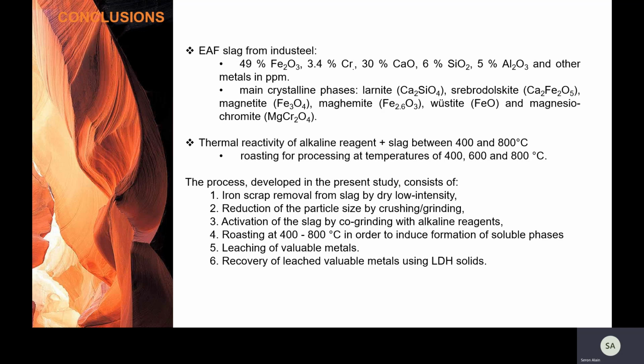TGA results clearly demonstrate the reactivity of the alkaline reagents mixed with slag when treated above 400 degrees C. Consequently, the roasting temperatures chosen in this study are 400, 600, and 800 degrees C. The process developed in the present study consists of iron scrap removal from slag by dry low-intensity magnetic separation, reduction of the particle size by crushing and grinding, activation of the slag by co-grinding with alkaline reagents, formation of soluble phases by roasting between 400 and 800 degrees, leaching of valuable metals, and finally, recovery of leached valuable metals using LDH solids.